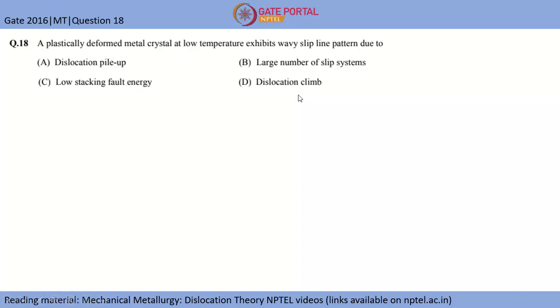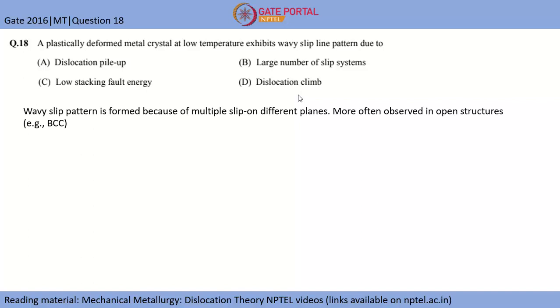So in order to answer this question, first we need to understand what is a wavy slip line pattern. Basically a wavy slip line pattern is formed because of multiple slip on different planes. Let's say we have 2-3 different planes and on those multiple slip is occurring, and more often it is observed in open structures, like BCC, where we don't have any close packed plane as such. Like in FCC, 111 is the close packed plane. In BCC, although we consider 110 as a close packed plane, it is not actually so if you calculate the planar density of that plane. Hence wavy slip pattern occurs in those systems.